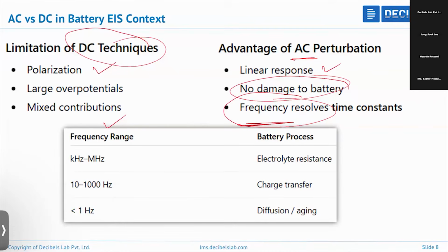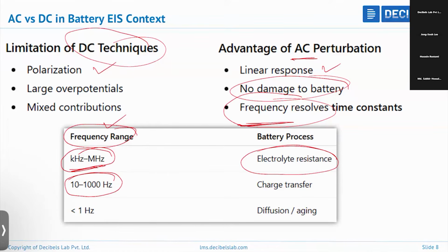So this frequency that we apply, perturbing the system, varies from millihertz to megahertz. In the kilohertz to megahertz range, you can extract the electrolyte resistance. At lower frequency, in the range of about 10 hertz to 1 kilohertz, it gives information about charge transfer. Then less than 1 hertz, at very low frequency, is the diffusion, meaning the intercalation of the lithium ion and the mass transfer in the solution and also in the electrolyte. That information can be extracted at this frequency. So the various frequency ranges give the information about the behavior of various components in the battery.